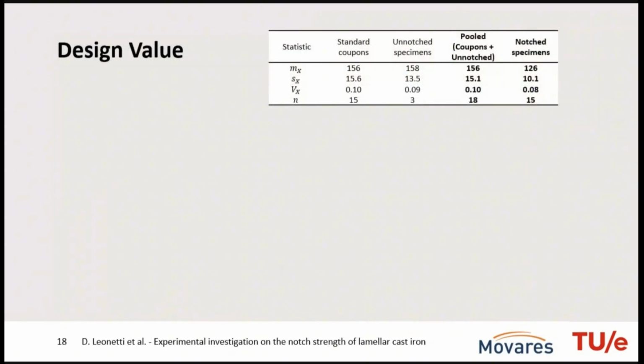So then we pooled, indeed. You can see here the two pooled data series with some statistics: the mean, standard deviation, coefficient of variation, and number of samples that are used to come up with these statistics. And then we followed the approach in the Eurocode 0, Annex D, which is design assisted by testing. So essentially, you can come up with a design value of strength to use for actual design. And this is the equation for coming up with the design value.